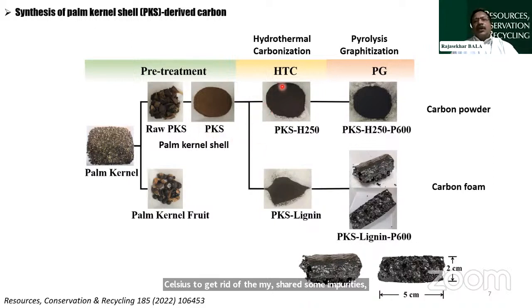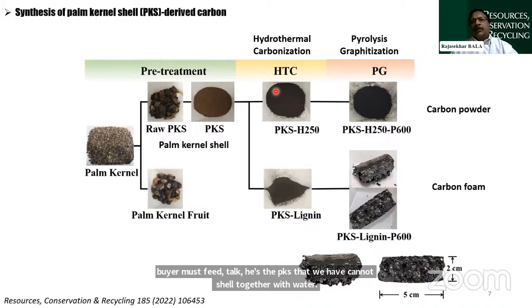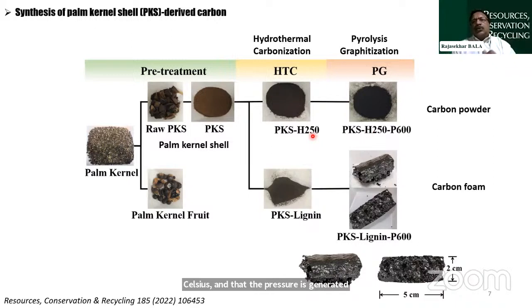Afterwards, what we have done is the hydrothermal carbonization, which is more like a pressure cooker in simple terms. So you have a closed vessel, you add your biomass feedstock, which is the PKS, the palm kernel shell, together with water. You completely seal the reactor, you heat it up to about 250 degrees Celsius, and then the pressure is generated automatically because of the closed vessel. Under those conditions, you can do the depolymerization of biomass into various fragments. In particular, we are talking about lignin, and that in turn can lead to carbon foam. So this is what is usually done.